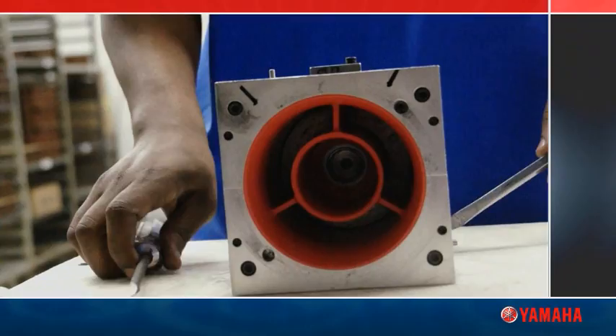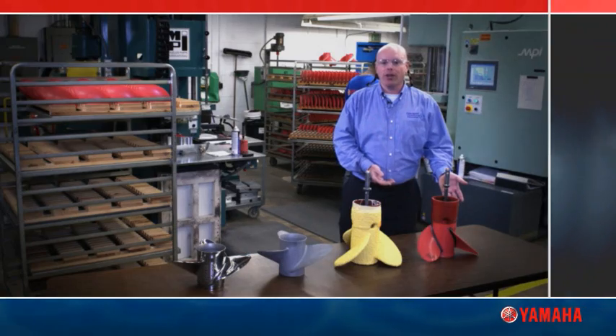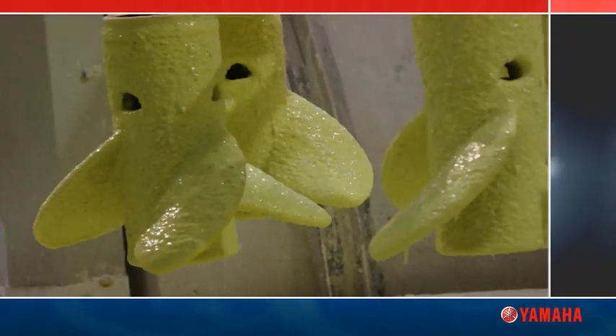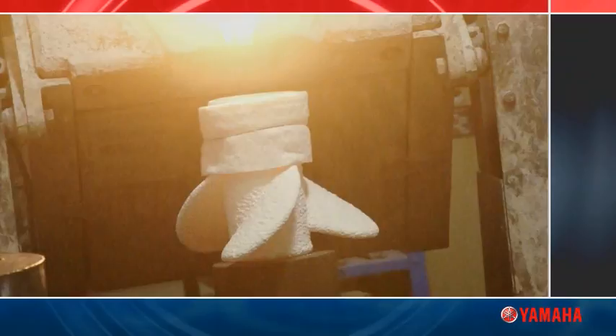This is an investment casting facility. In this case, investment means to encapsulate. First, we make a positive — a wax version of the propeller. Then we build up a multi-layer ceramic coating around it. From there, we melt the wax out and use that as a container to hold the molten stainless steel.